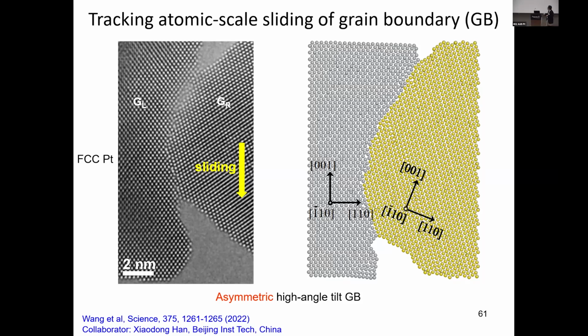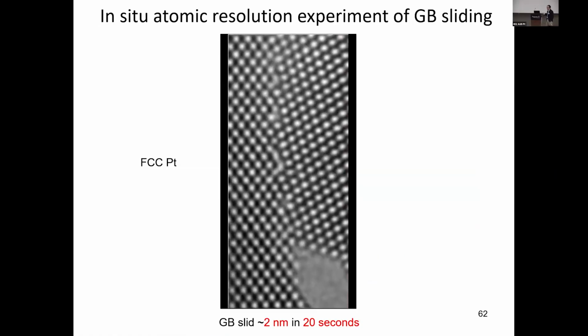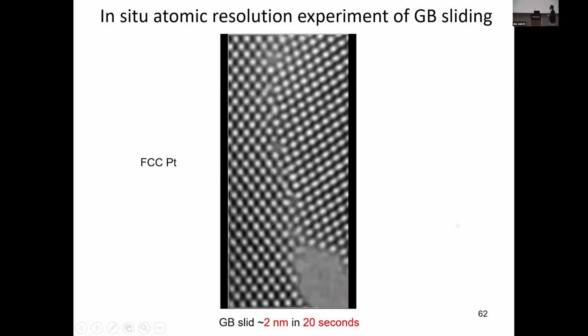Now we can further resolve this atomic structure and heterogeneity to understand their impact on the mechanical behavior. In this case, I want to demonstrate our in-depth fundamental study using the in situ high-resolution TEM experiment for a bicrystal straining experiment. This is an FCC Pt bicrystal with an asymmetric tilt grain boundary. We applied this shear load and studied this system through the direct high-resolution in situ TEM experiment and also atomistic simulation. As you can see, this in situ TEM experiment allows us to directly visualize this grain boundary sliding atom by atom and step by step.